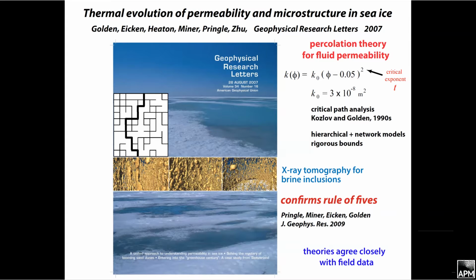All right, the next big step was to get a theory for how the permeability of the sea ice depends on the temperature, and also to confirm our rule of fives, because we didn't really have any direct evidence that there was a real percolation threshold in the brine microstructure. But we developed an X-ray tomography method, which finally demonstrates this. It took a long time, but we finally did this.